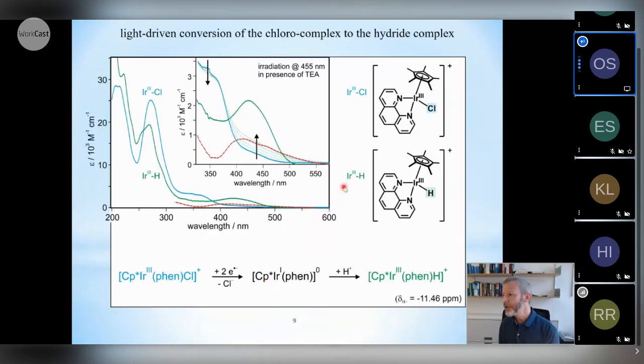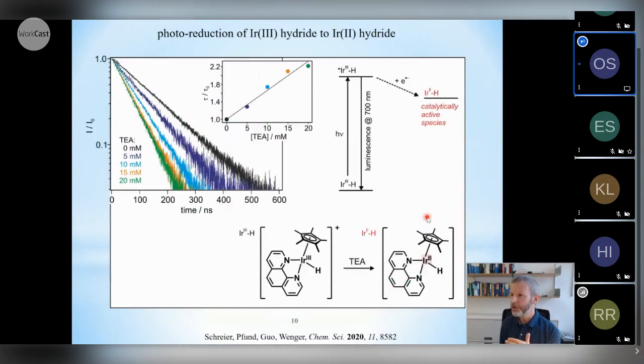Now, this iridium-3 hydride complex is, however, not yet the catalytically active species. When we let it sit in the dark along with the substrate, nothing happens. So we need further light activation of that iridium-3 hydride. We can promote it to a metal to ligand charge transfer excited state, which luminesces in the red with a lifetime of roughly 200 nanoseconds.